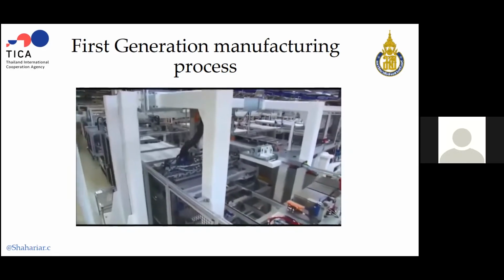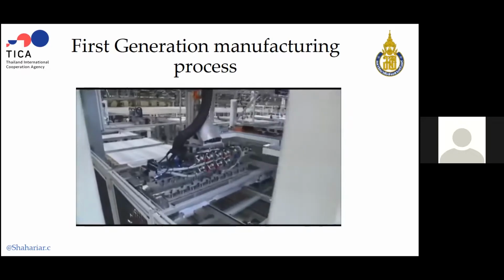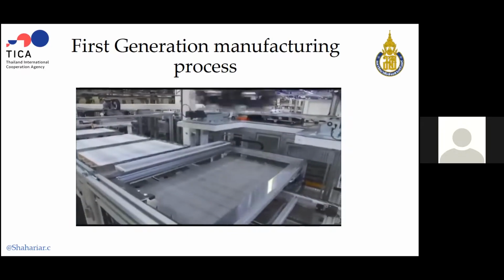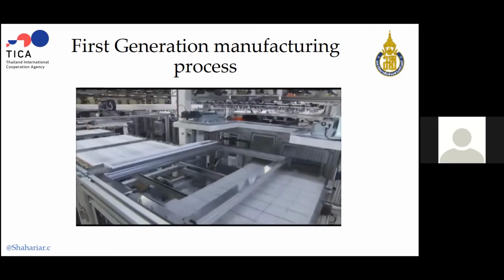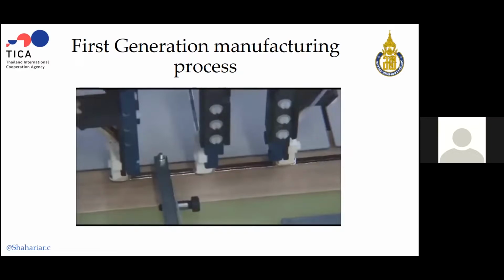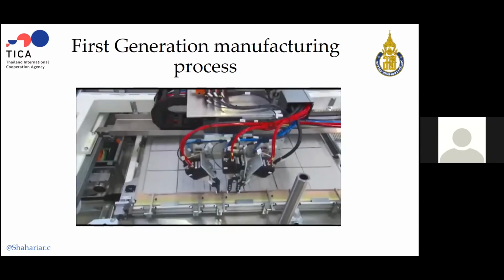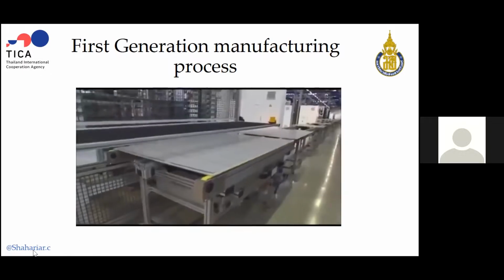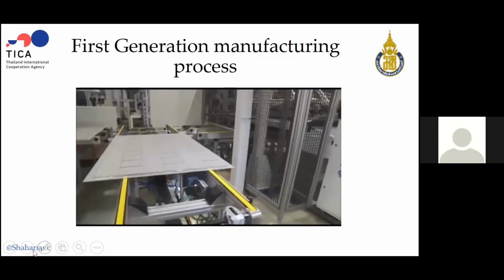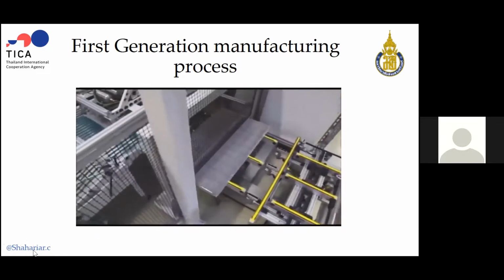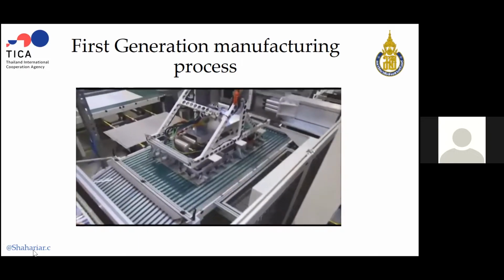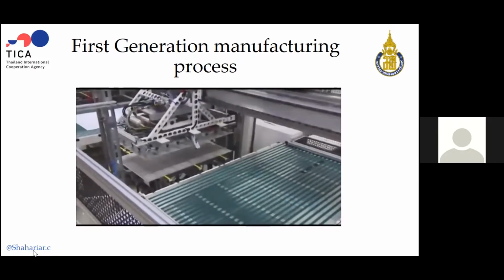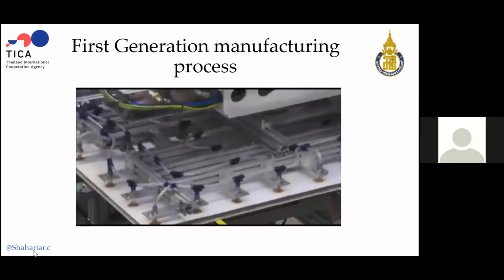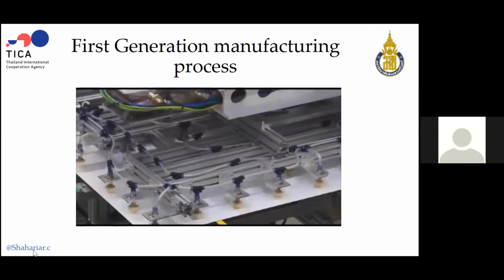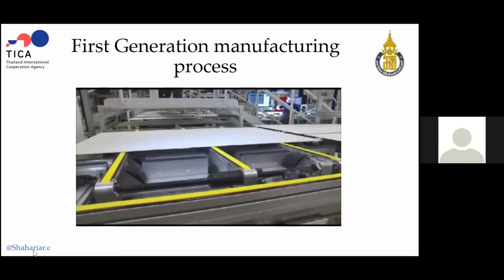6 of these strings, laid next to each other according to the polarity, create a matrix of 60 solar cells. The cell strings are then soldered together in series, so that the module delivers a total power of 245 watts DC. Now properly mounted on glass, the future module is sent on to further production steps. It's given a second transparent EVA film and a very robust rear film that resists the system voltage of photovoltaic systems of up to 1000 volts without any problems.